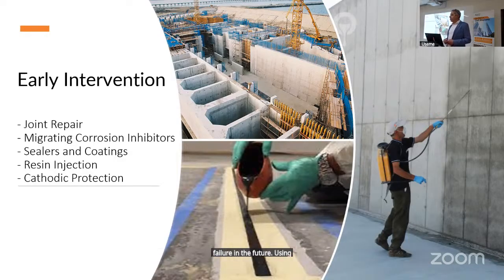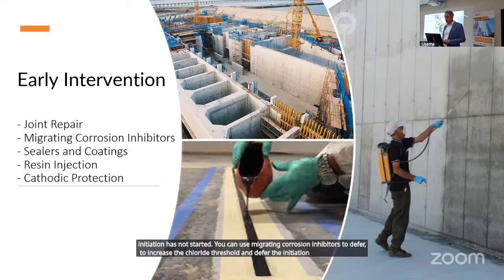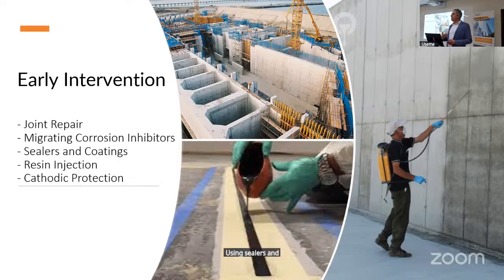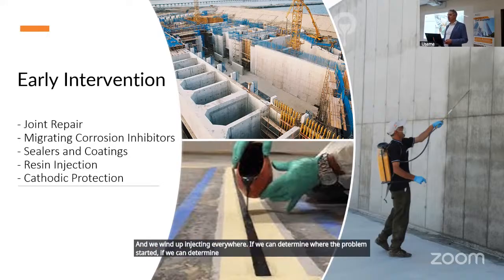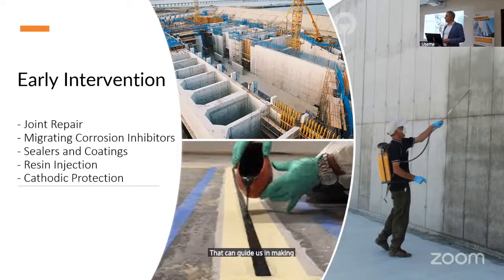Using migrating corrosion inhibitors that can be surface applied when we know that the chlorides are going through, but initiation has not started, you can use migrating corrosion inhibitors to increase the chloride threshold and defer the initiation of corrosion. Using sealers and coatings to delay the ingress of chlorides. Resin injection. In many cases, we have failures in basements, and we wind up injecting everywhere. If we can determine where the problem started, if we can determine the real root cause of the problem, that can guide us in making those decisions in repair and having more effective repairs.